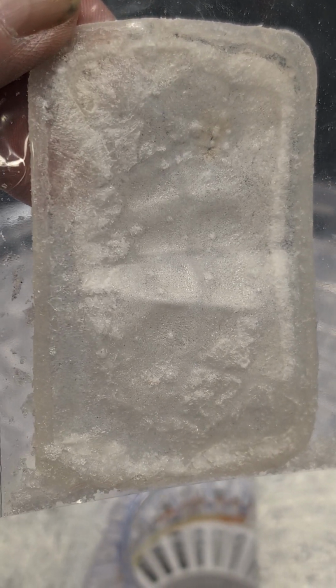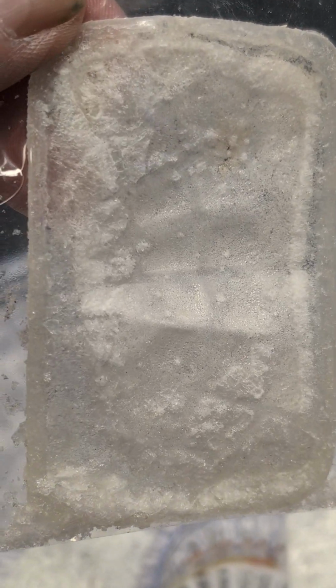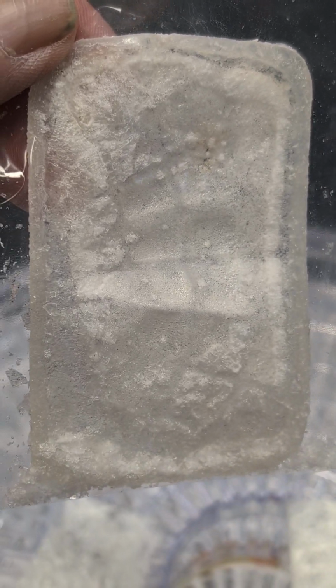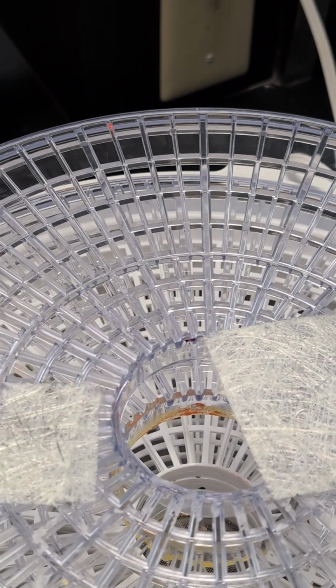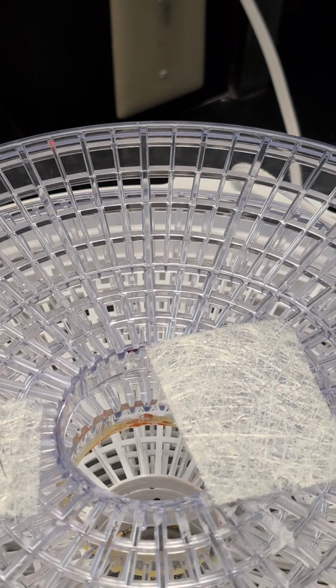Now, to compare, here is a sample that I dehydrated 24 hours. There's no aluminum. There's no fiberglass mat. This is simply a Agar Agar gel, which was cross-linked with glutaraldehyde. I have another video describing that. And then bathed in a saturated potassium chloride solution. And I left it overnight and then dehydrated it. It went from about 16.04 grams, the swollen gel, down to 6.07 grams, and that will be vacuum sealed until I need it.